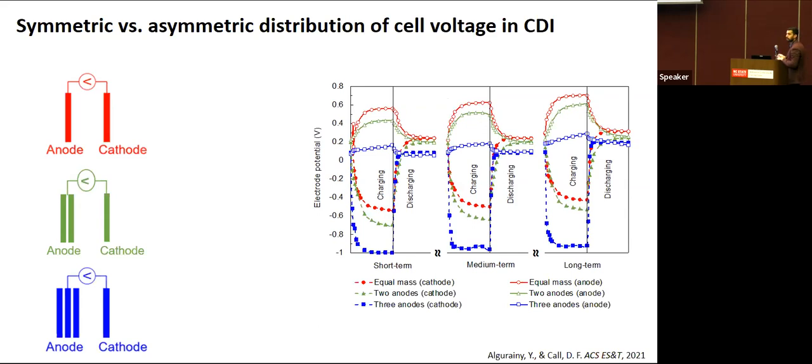We added more carbon to the anode now, so the mass ratio of anode to the cathode was 3-to-1. By doing so, the electrode potential was further driven more negative. So what that means is that, in each of those cells, the anode was exposed to a different level of oxidation potential because of the negative shifts that we added by controlling the mass ratio of electrodes.